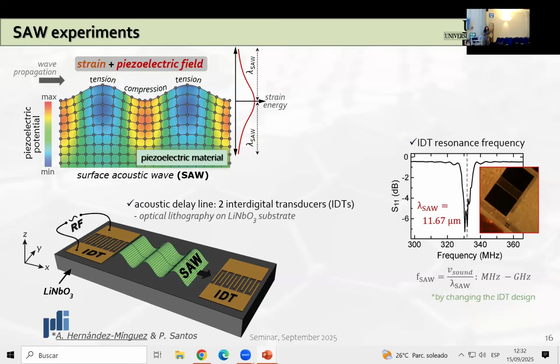For these particular experiments, these IDTs were designed to operate at around 330 megahertz, but the acoustic frequency can actually span quite a broad frequency range, from a few megahertz to several tens of gigahertz. And this can be achieved simply by changing the design and the size of these IDTs.